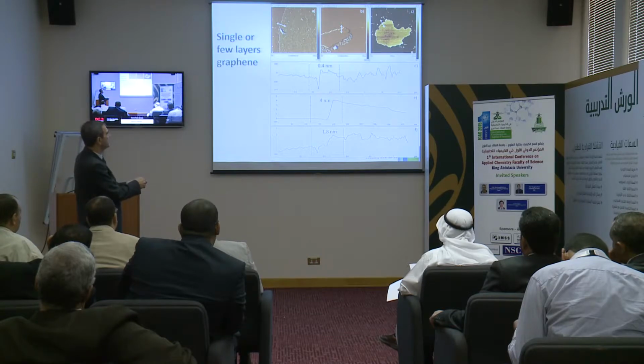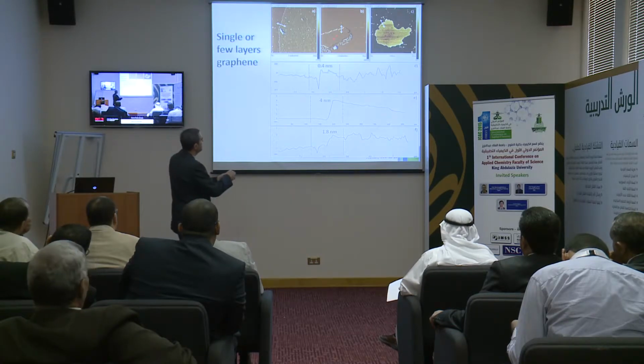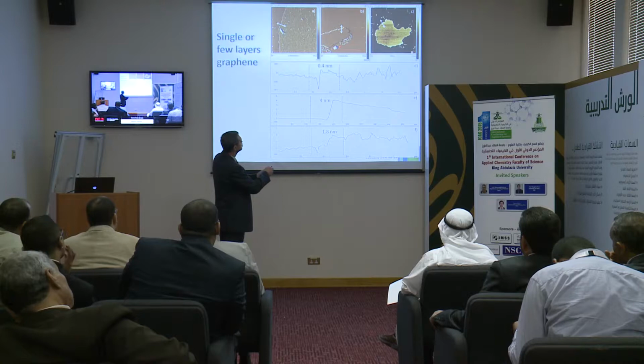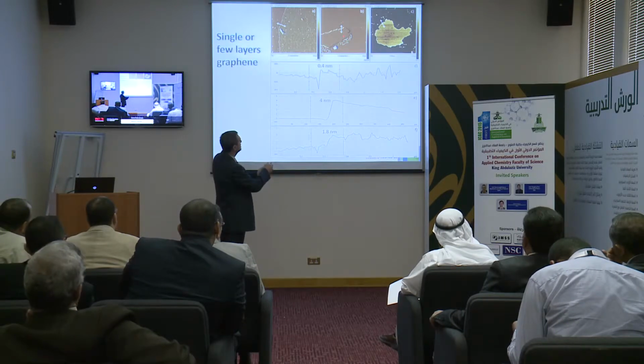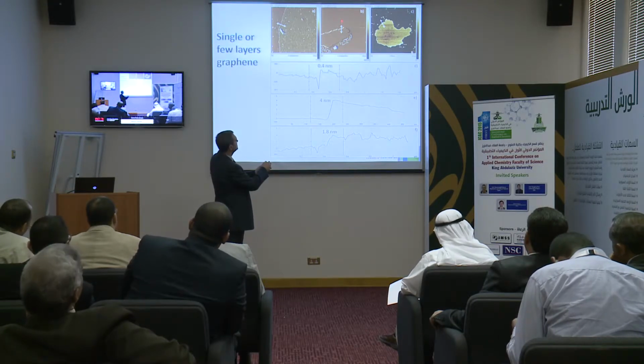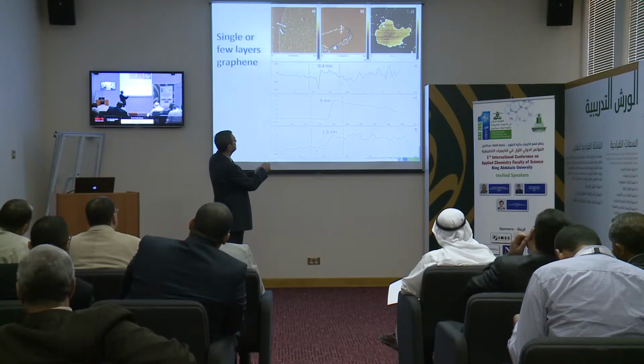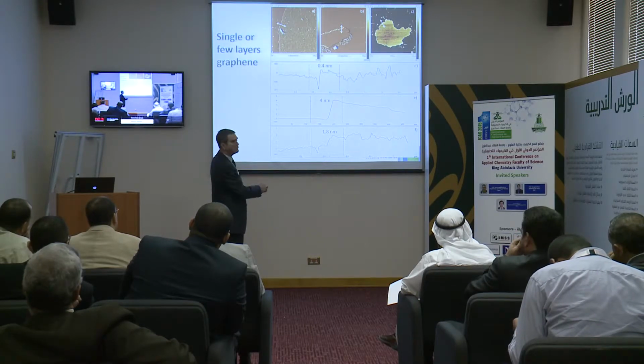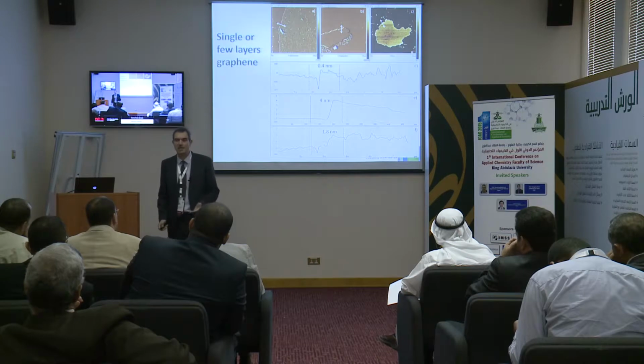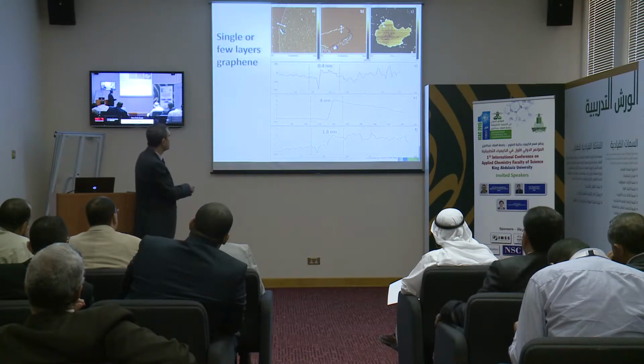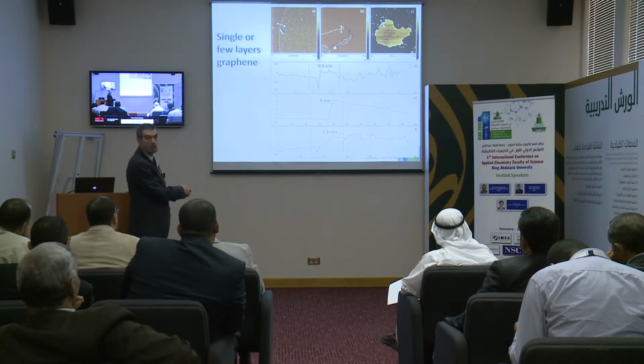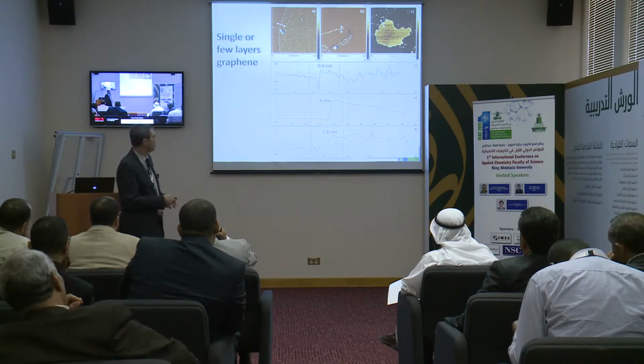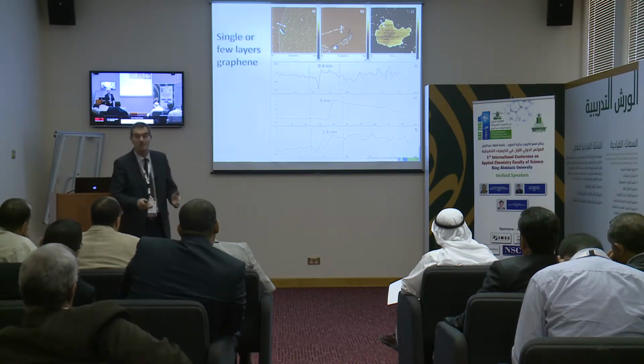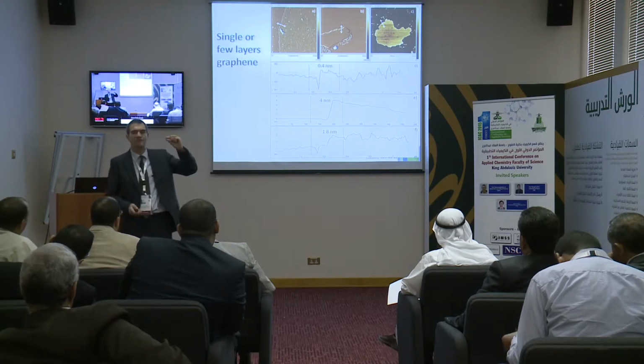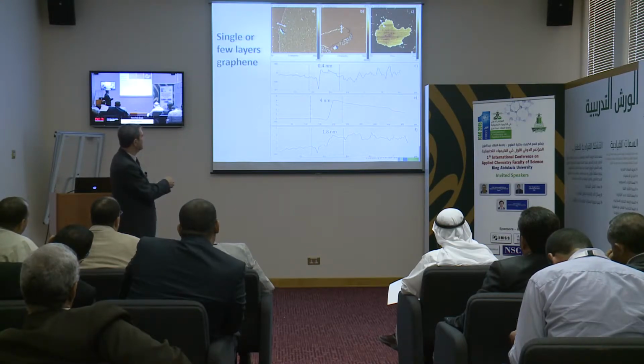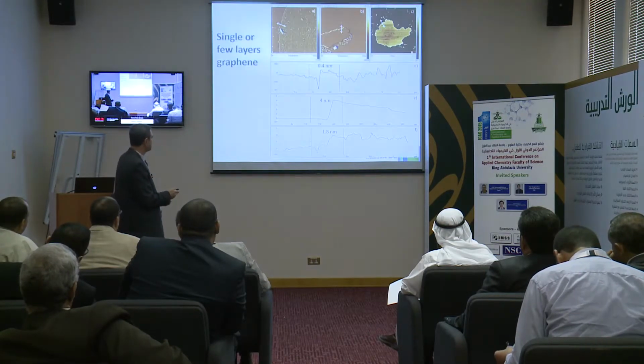For instance, in this case B, even in the frontal image you can see that there are some layers here, some terraces, but measuring the difference in height between this point and this point, you observe that it is 4 nanometers. 4 nanometers is about 10 layers of graphene. Of course, here, because we have 4 nanometers, the noise of the measurement is much lower. Whenever you go to the limit of the technique, because we have only a 1 atom thick layer, then the noise is much higher, but this is normal.